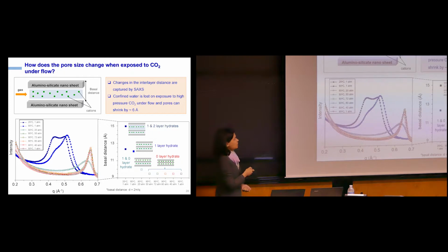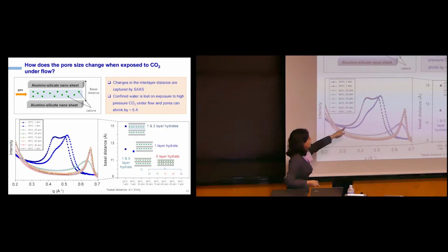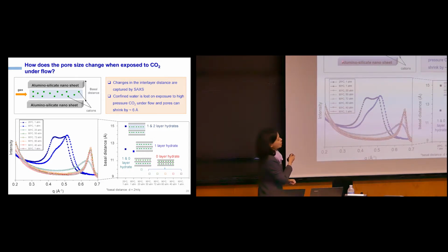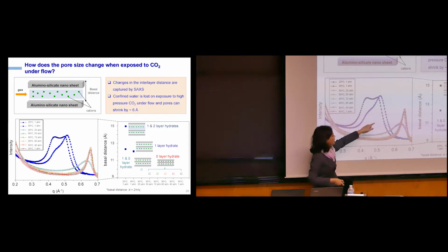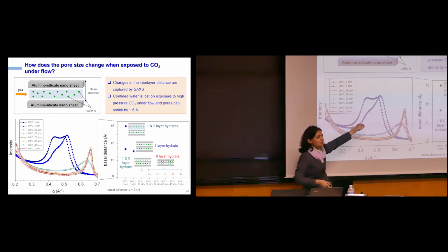But on the other hand, if you're dehydrating it, then you would expect this to shrink. What we find is that as we go up in temperature and as we go up in pressure, for example, if you're at 90 degrees centigrade at 80 atmospheres, this two-layer peak corresponds to the scattering from this one nanosheet and this interlayer basal spacing, right? That is the basal distance right here. If we have two peaks, one is indicative of a one-layer hydrate, the other one is indicative of the second-layer hydrate. So this is two mixed states of one and two-layer hydrates.